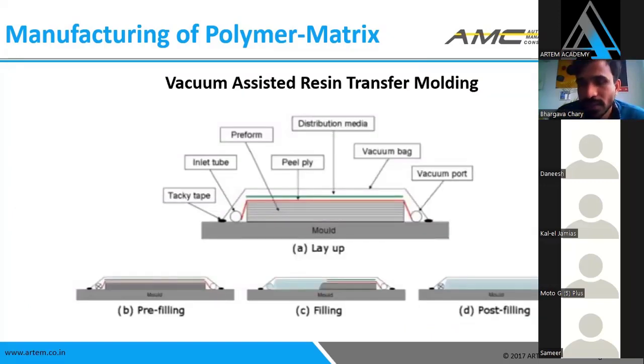So this is the VARTM process, vacuum assisted. Here, if you see, this is a mold or a shape, for example. The fibers, these mats, are placed, and on top of the mats we use a breather, which spreads the matrix, and then it is closed completely by the vacuum bag. A vacuum is generated using a compression cylinder. There's an inlet for the resin to enter, a vacuum bag on top of it, and then a compression cylinder. As there is a compression cylinder, it sucks in all the resin material, so the resin spreads through the whole fiber or mat. Then it gets cured for around 12 hours or 8 hours, depending on the resin, and then the component is ready.